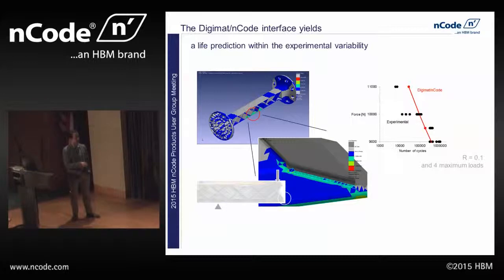And what we see is relatively good correlation within a decade or so for each of the 3 different cycles. We're definitely farthest out here at the highest loading cycle. And the question there becomes, we're starting to get down into the 10,000 cycle range. For these types of materials, is this still really high cycle fatigue, or are we starting to see some damage accumulation?